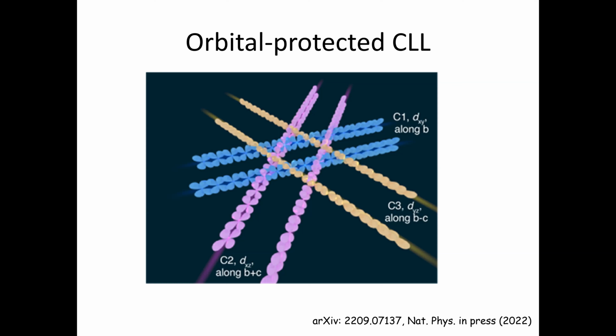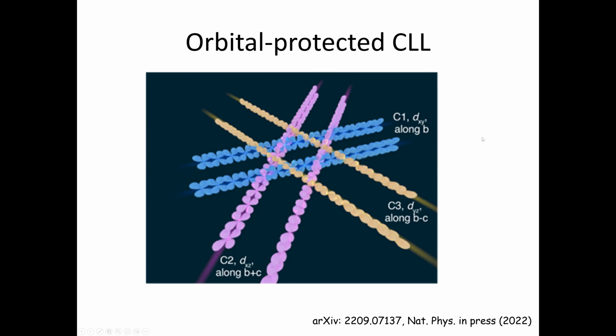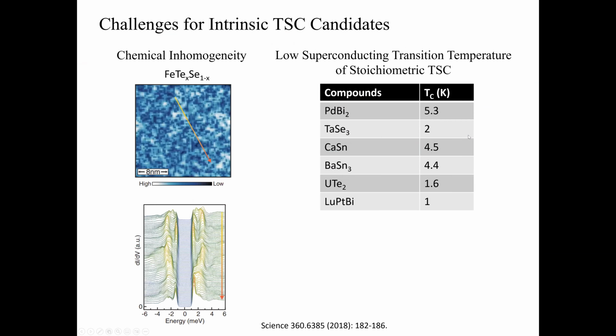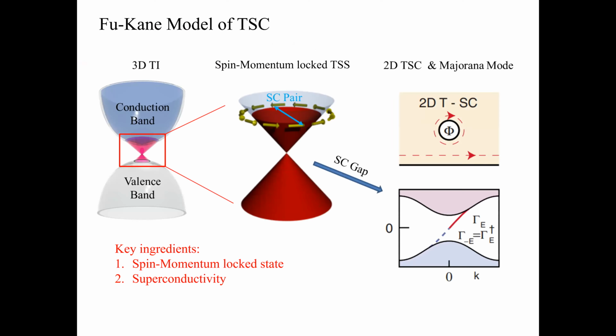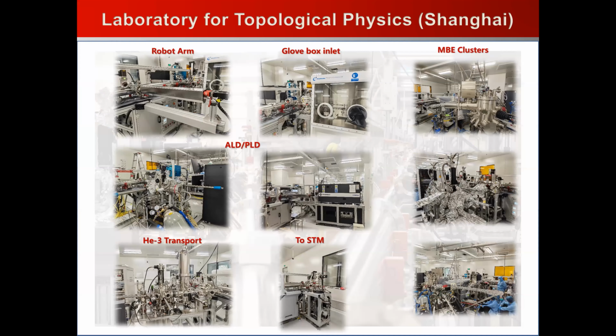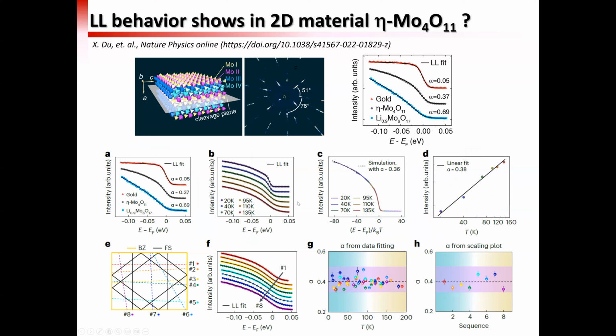So what's the temperature? Sorry, what's the temperature you have for this material? You mean the measurement temperature? Yes, when you measure this material. When we measure this, it is actually the Luttinger liquid behavior. I think we were able to see it over a broad temperature range. Let me see. We vary the temperature from 20 Kelvin to 135 Kelvin, so a pretty broad range. They all show this behavior.